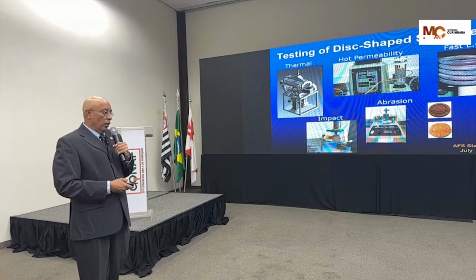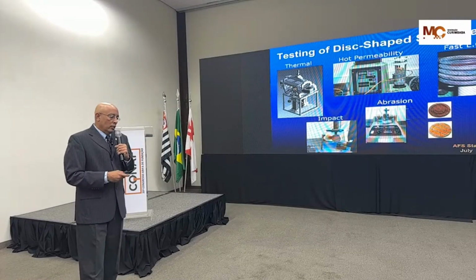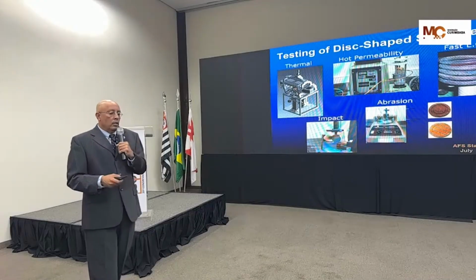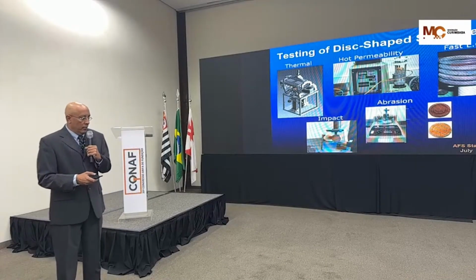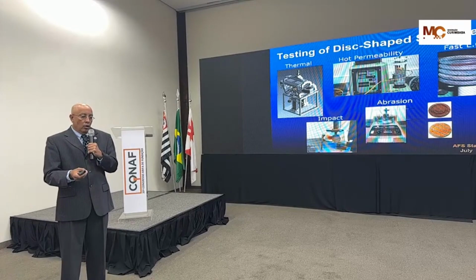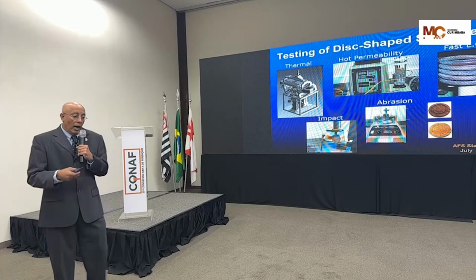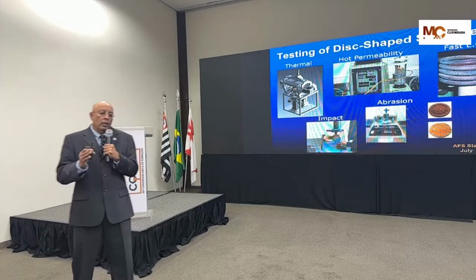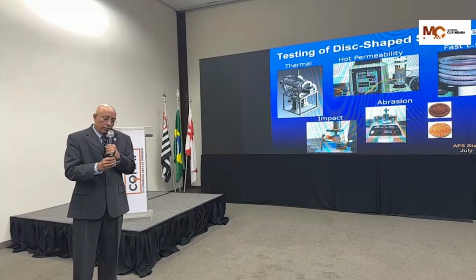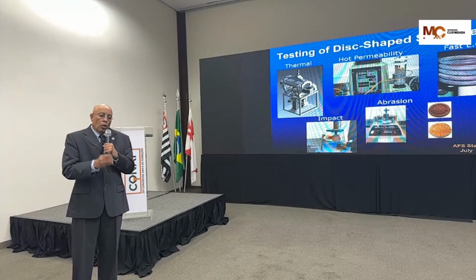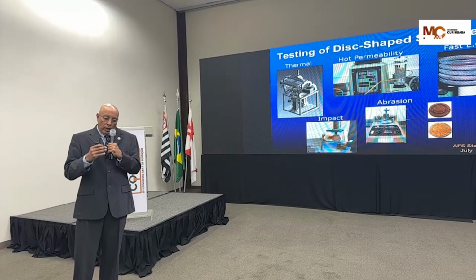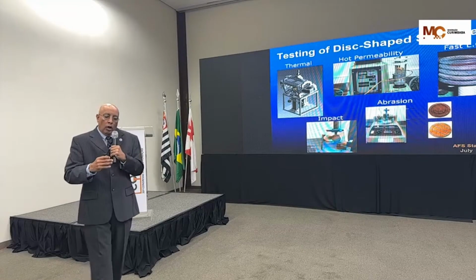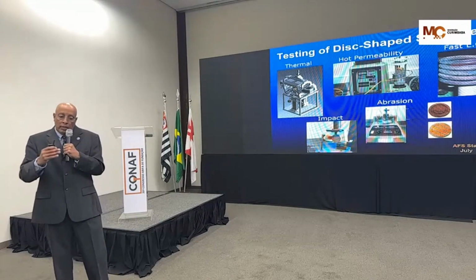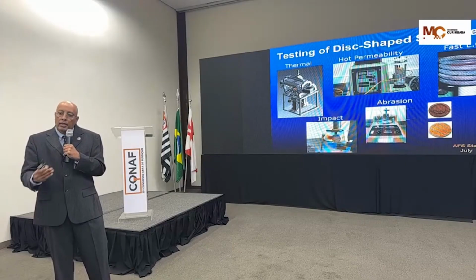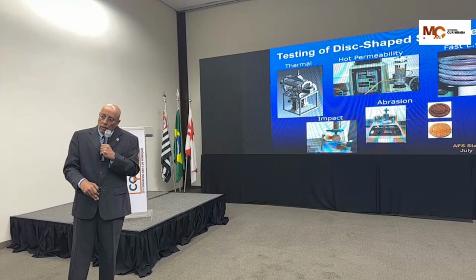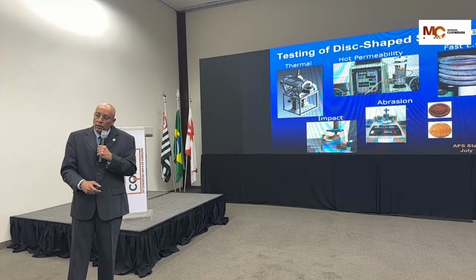The reason that we run the permeability test hot is because at ambient, the permeability is only telling us how fine or coarse our sand grains are. But when, again, the metal meets the mold or the heat touches the cookie, we now see either a condensation layer or a gelatinized layer blocking the interstitials of the sand grain that will reduce the venting characteristics or the permeability of the sand.